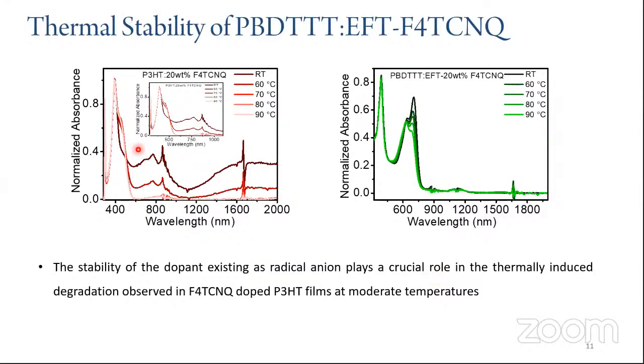So as we have compared in the Raman spectra with the P3HT system, here we can see that upon increasing the temperature, that is at a moderate temperature itself from 60 degree to 90 degree, the P3HT F4TCNQ system shows a rapid decrease in the anionic absorption as well as the polaronic absorption in the NIR region. So this decrease is due to the thermal instability of such systems, and the thermal stability is another major factor that governs the functionality of a thermoelectric system, since we deal with temperature application over the compound.